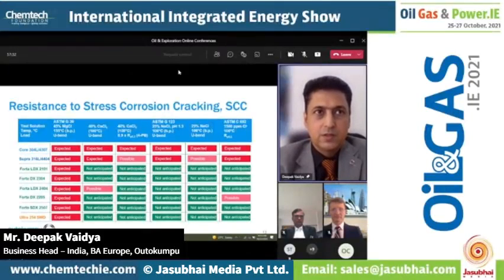We did one test in India, done by a third party, wherein we provided them samples of SDX 2507 for Indian Oil Corporation, and the sample lasted for around 329 hours. Which means that compared to other grades of stainless steel, this worked very well in India.